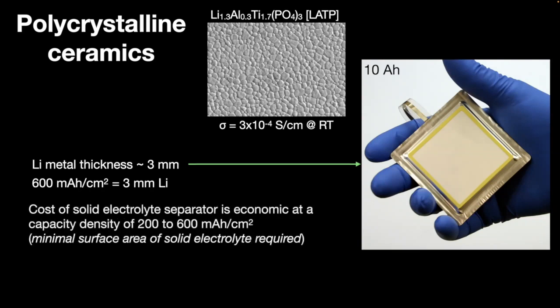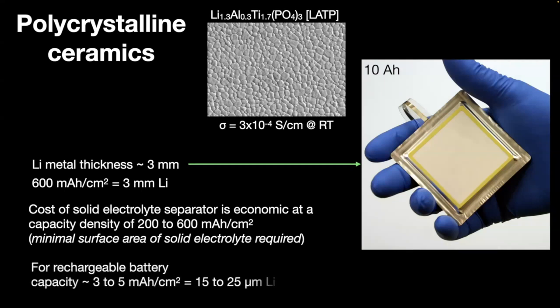So in this application, where we're using these types of ceramics to build very unique high energy density batteries, we don't need much of the solid electrolyte because the capacity density is so high. And that makes a big difference in terms of downstream costs. So this is an affordable approach for a primary battery that has very high capacity. It's going to be different when we start looking at rechargeable batteries, quite different. And it's just a simple mathematical calculation to see the kind of trouble you get in.